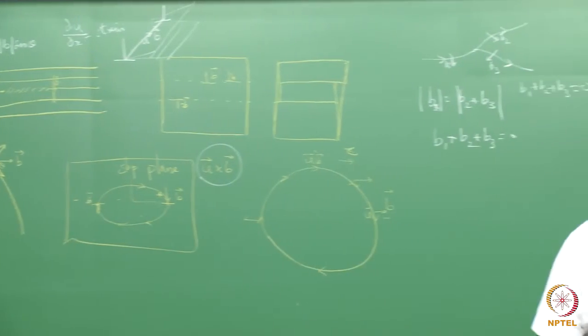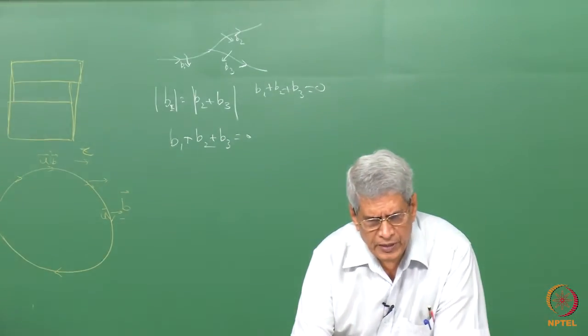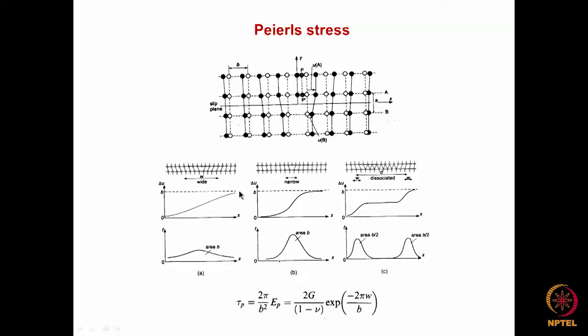So from this you can make out that beyond a particular distance, though displacement is going to be there with respect to origin, that strain, if you try to calculate it, will turn out to be 0. The maximum strain is going to be at the center, correct? So that is what essentially is being shown. But if you see how the displacement is taking place, it is a very gradual one.